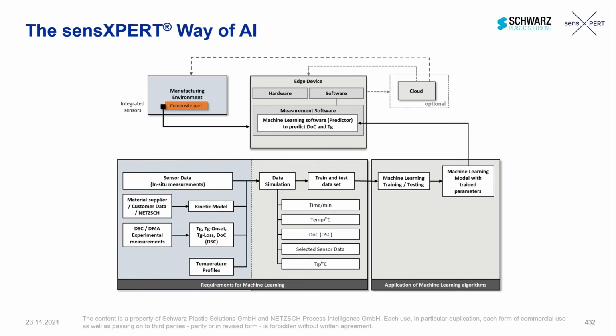Therefore, we have our own way of doing artificial intelligence. We simulate our own data sets based on reaction kinetics, real process data from the environment we are installed into, and we combine current quality criteria of our customers, whether it is degree of cure, determined with a differential scanning calorimeter from the lab, or the elastic modulus determined via dynamic tests. Whatever our customers have as a standard today, we can use, and we can simulate the data sets we need based on the first measurements out of a real mold, combined with material science, to be able to simulate different states of the material.